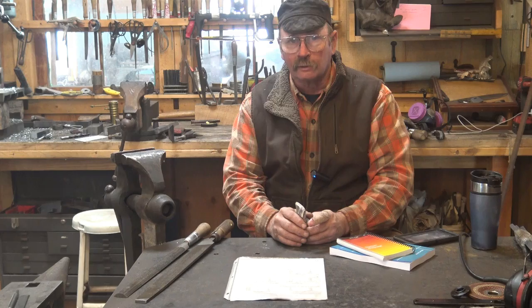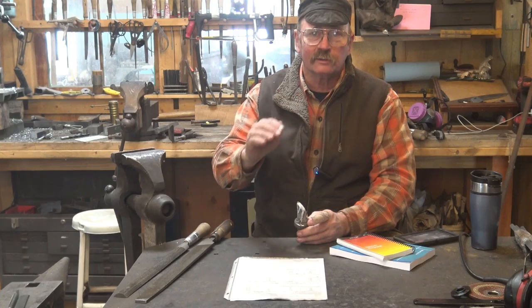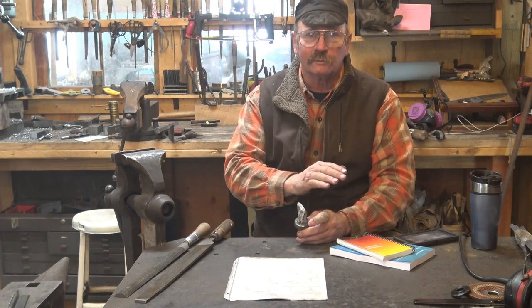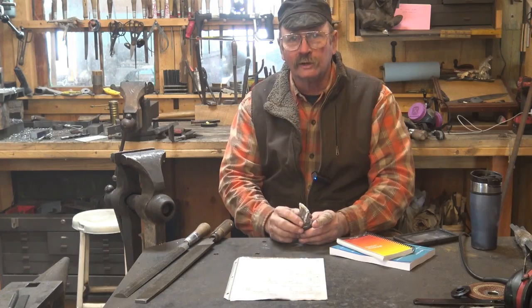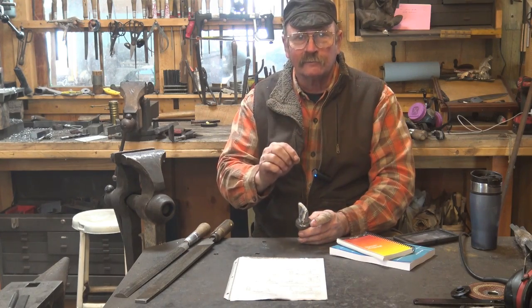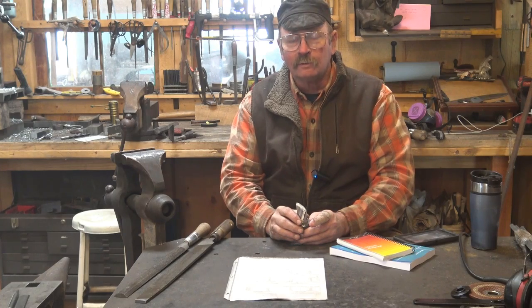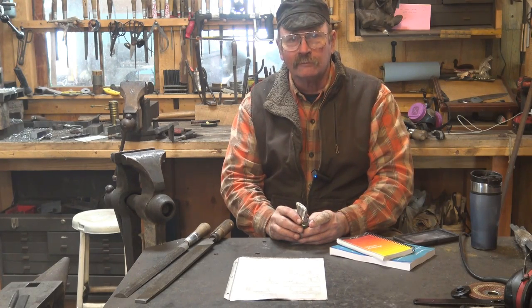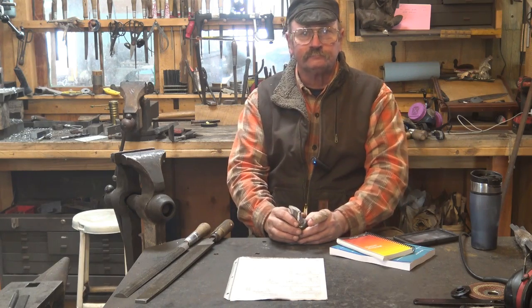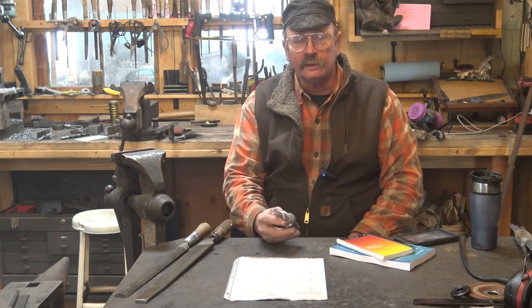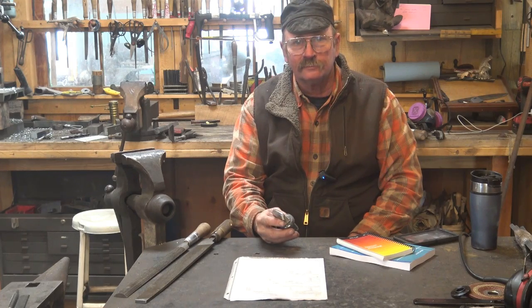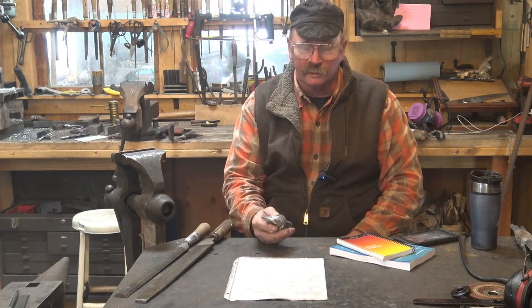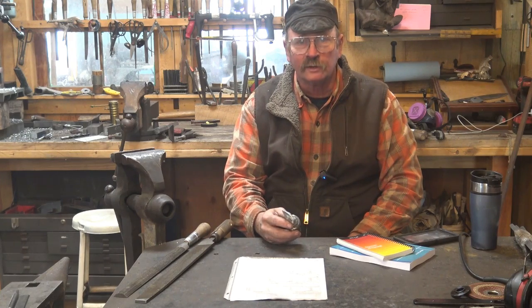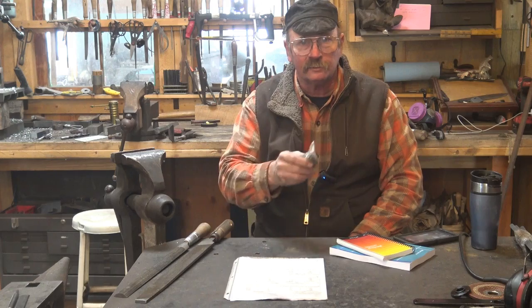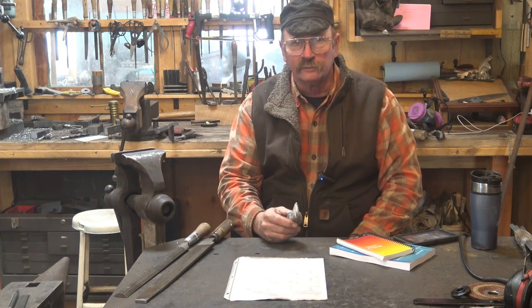Industry standards would not agree with us. They have formulas for every steel: bring it up to this temperature, cool it this many degrees per hour till it gets to a certain temperature. And it can be a 24-hour process of controlled heat reduction after it gets to that critical temperature. And in the blacksmith shop, we're just not that picky, and we don't have the ability to worry about a lot of that stuff. So we're generally pretty satisfied with annealing by letting it slow cool in vermiculite. It's not the absolute best, but if you stick with fairly basic, fairly simple steels, it's more than sufficient.